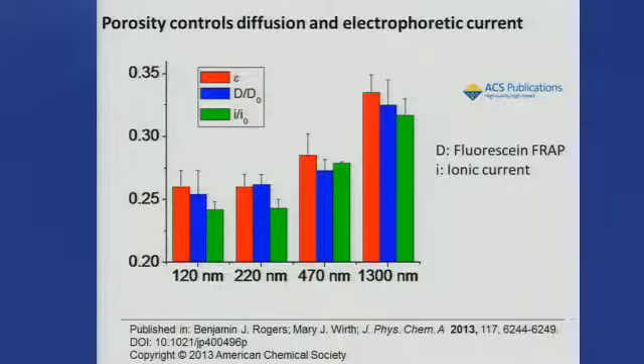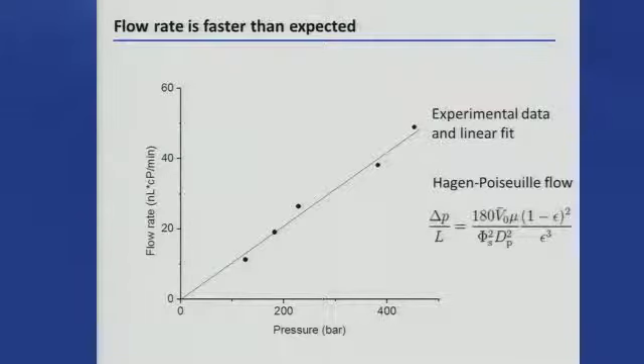So all looks good, but sometimes you run into things that are really funny. A few years ago, we published a paper using electrochromatography, and in the supporting information, we just mentioned that you could actually flow through these. We didn't know whether you could really flow through these with any reasonable efficiency or not, but we found that you could, and it was a collaborator of ours who had a really high pressure pump. We shipped her these capillaries, she measured them, and we got these really nice flows.